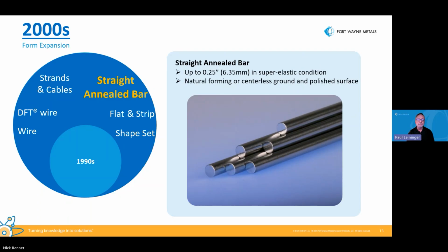Our straight anneal bar is also a new offering that began in the early 2000s. This is straight anneal bar that features the super elastic properties you're probably somewhat familiar with in terms of nitinol. In terms of the size range offering here, at the lower end, we can offer 0.1 inch in diameter or 2.54 millimeters, all the way up to and including quarter inch super elastic bar, 6.35 millimeters. Some common surface finishes that we have here are natural forming oxide and our centerless ground and polished surface options.